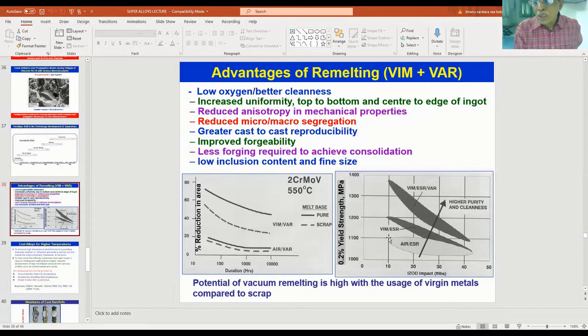If you are using vacuum induction melting and electroslag refining, you see that strength has gone up. If you have used a triple melting process, VIM, ESR and VAR, this has gone up clearly. And what you have to choose is, don't use the scrap. When the scrap is there, the properties you get will be lesser.